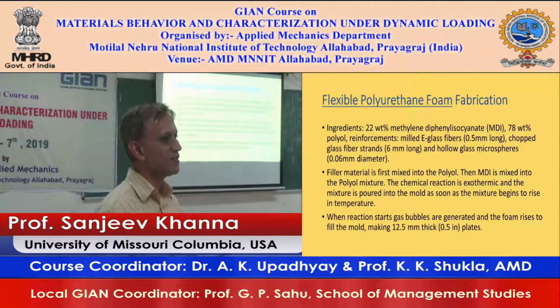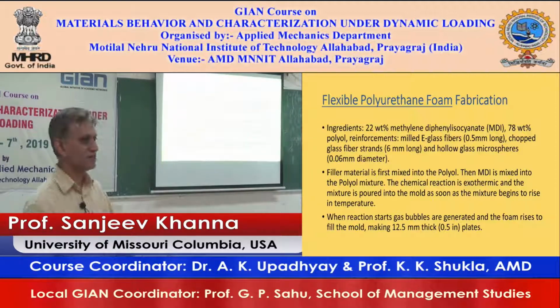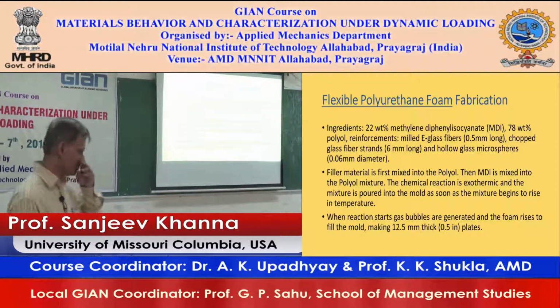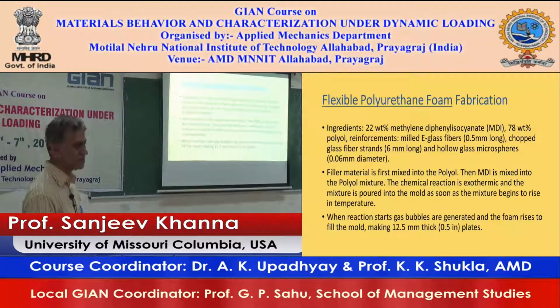So these were about 0.06 millimeter diameter, but that's the average diameter. It varied between about 40 to about 100 microns. Okay. The filler material is first mixed into the polyol, okay, and then MDI is mixed into the fiber reinforcement and the polyol mixture. Chemical reaction starts, it is exothermic and it begins to get warm.